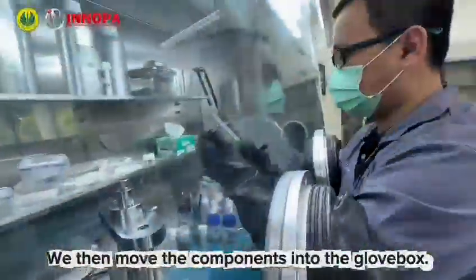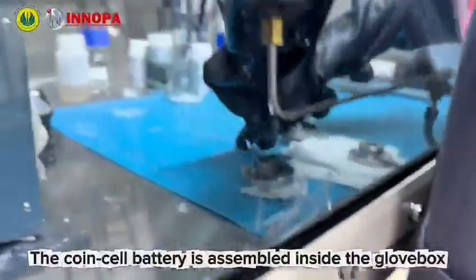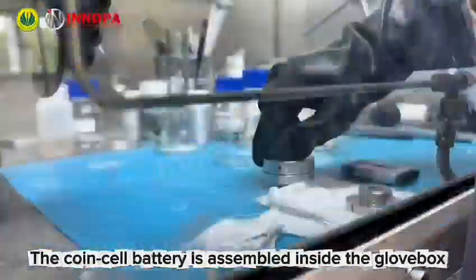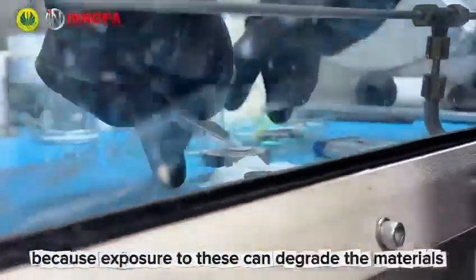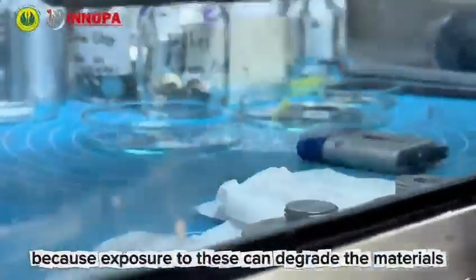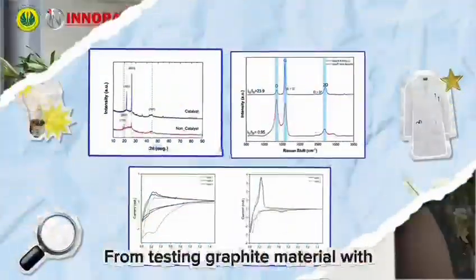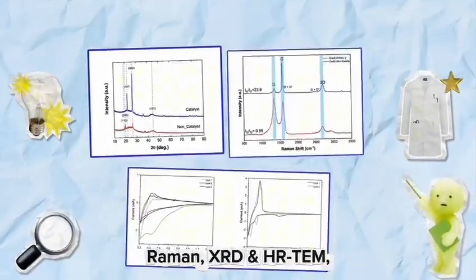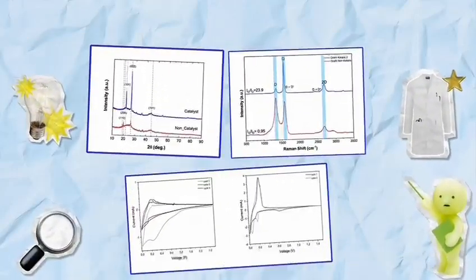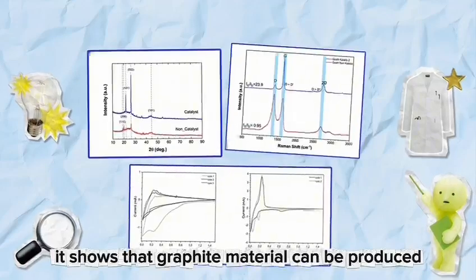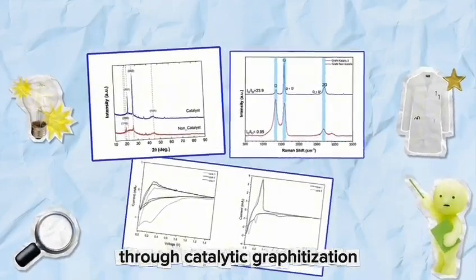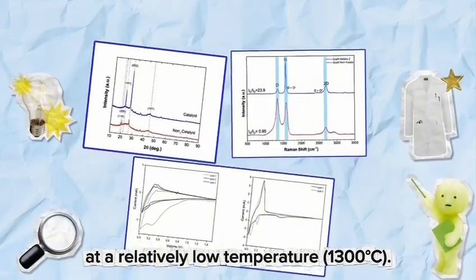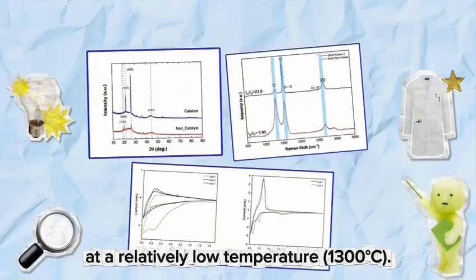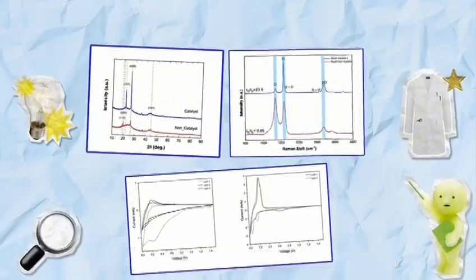We then move the components into the glove box. The coin cell battery is assembled inside the glove box because oxygen and moisture must be excluded, because exposure to them can degrade the materials or potentially cause a fire. Testing graphite material with Raman, XRD, and HRTEM shows that graphite material can be produced through catalytic graphitization at a relatively low temperature, which is 1300 degrees Celsius.